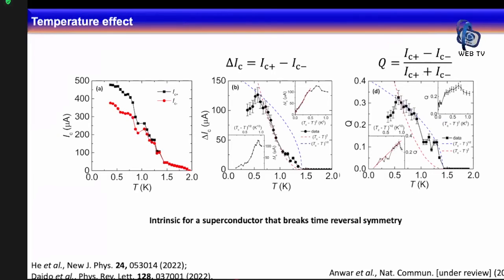And so if it is decreasing with the temperature, then we can take the difference of the critical currents, that we can call the non-reciprocal component. The non-reciprocal component means how much difference there is between positive and negative current. And as a function of temperature, you can see if we apply the very recent theoretical models, because this research was initiated 2 years back, but this year a lot of work has been done, not only on the experimental side, but also on the theoretical side. And these recent theoretical models very nicely explain our result, that it is the effect coming from a superconductor because of broken time reversal symmetry.